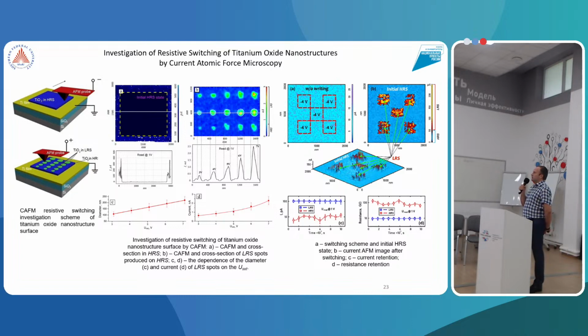On the figure on the left side, we can see initial high resistive state of the structure after formation. After that, we switch the local areas on the surface by applying different voltages from 3 to 7 volts and produce current atomic force microscopy scanning and provide the visualization.